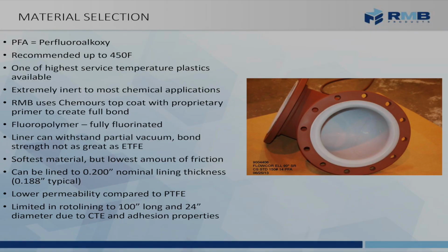But if the temperature exceeds 302 or if the service environment requires it, the next step is going to be PFA. This is pretty much inert to all chemical streams. So this is going to be lined to about a 3/16, and it's going to be a two-part process with a primer and a top coat. It's limited, though, in size because once the sizes get above 24-inch diameter, it can tend to delaminate. So we have learned over the years just to limit this to 24-inch diameter and 100 inches long.